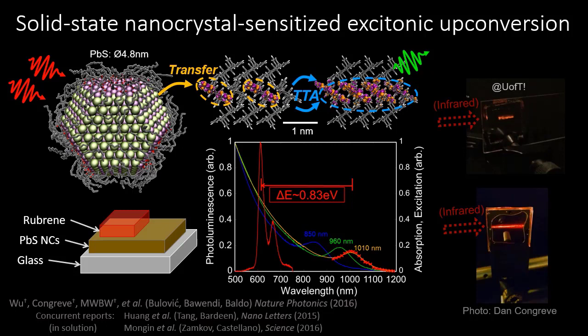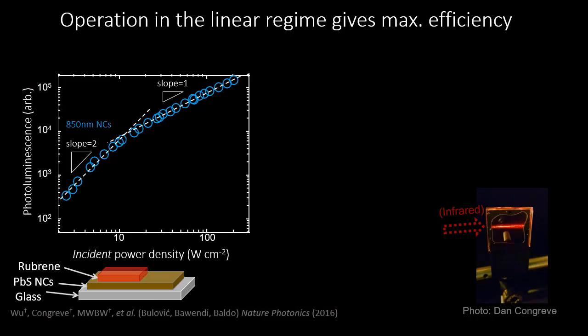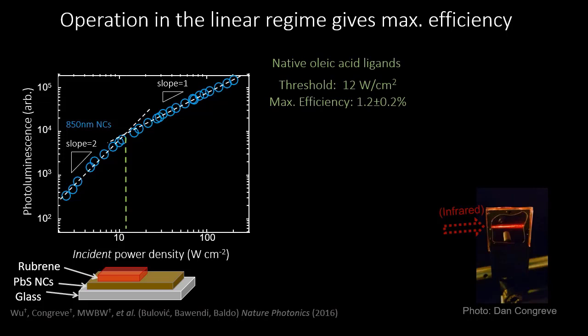I'll also point out the work that happened at the same time from Ming-Lee Tang and Chris Bardeen at UC Riverside, and Mikhail Zamkov in collaboration with Phil Castellano, who also put out nanocrystal-sensitized work at that time. Regarding how well it worked: I want to explain this plot because we'll return to it in the dimeric upconversion discussion. Photon conversion is a second-order reaction in photons, so there's not just one efficiency — there are many efficiencies. You reach a saturating efficiency once you're driving the system hard enough for the second-order process to dominate. In the first devices, efficiency was relatively low, around 1%, with a threshold of about 12 W/cm², which is about 100 suns — far too high for a practical solar cell, but good for a proof of concept.